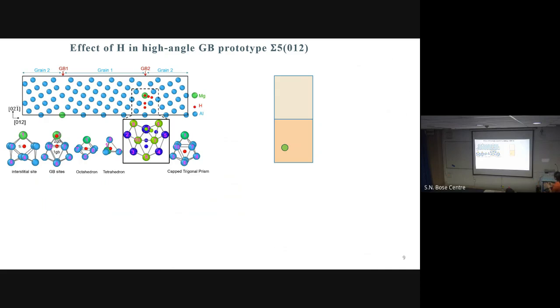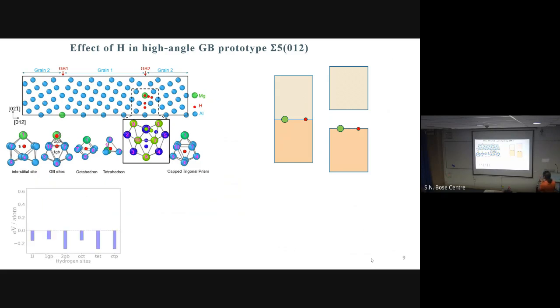Suppose there is a grain boundary, there is a solute element, magnesium here, and it is migrating to the grain boundary. Then there is diffused hydrogen, and it is also coming to the grain boundary. And after both of them are in the vicinity of each other, they are forming a free surface. So we are trying to evaluate the energetics of this situation.